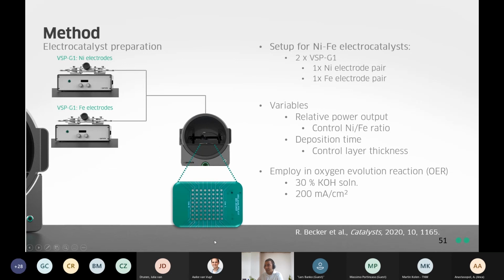How this was done is we took their wafer and we placed it in the printer. The printer was equipped with two VSP-G1 nanoparticle generators. One of these had nickel electrodes. The other had iron electrodes, and what we could do is vary the elemental composition of the deposited material by varying the relative power output of the nanoparticle generator with nickel in it and the nanoparticle generator with iron in it. So in doing so, we could vary the nickel to iron ratio.